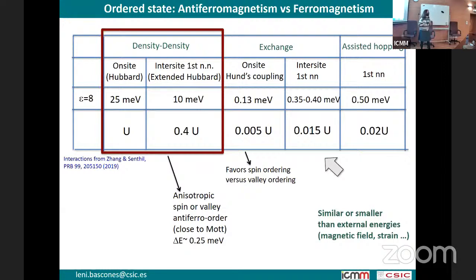So somehow finding ferromagnetism in this system is really not telling us anything about the nature of the system. I'm talking clearly about the moire close to the insulating state. What is interesting here is that these energies are similar to other energies that can come from our system, like magnetic field, like a strain, or something that maybe can help us to play with the system and tune, to see whether we observe, and maybe tune different magnetic states. That's something that could maybe be done.